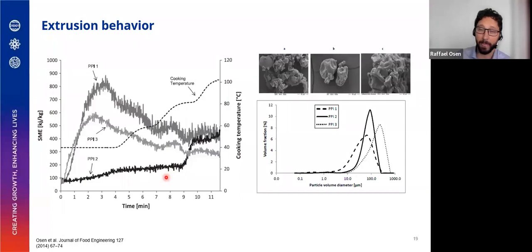And our first assumption was, well, maybe it's the particle size, that the particles of protein number 2 are just so large that it takes some time for them to swell, to take up the water and to really form a dough. And therefore we might see here this curve progression. Now, interestingly, looking at the particle size, we found that protein number 2 actually is just between the other two protein ingredients. So most likely this cannot really be the explanation for this behavior.